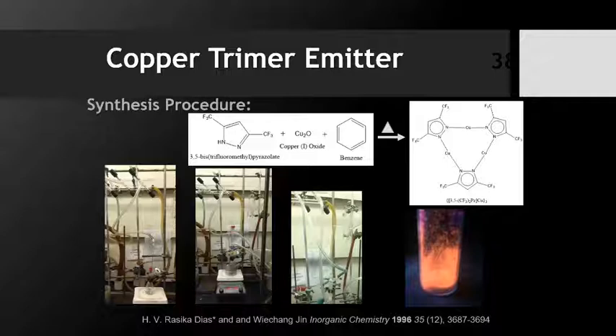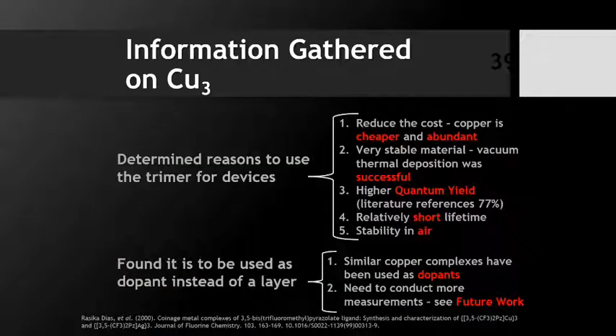So this is the synthesis procedure. We have just using standard Schlenk techniques, which I had to learn, and using benzene, a chemical. This is just the layout of the synthesis and what happens. And right here is our little product. You can see it's white. And when we put it under UV light, we actually get a really pretty orange color, which I thought was cool. So basically, after running lots of tests on our copper, this is what we found out.